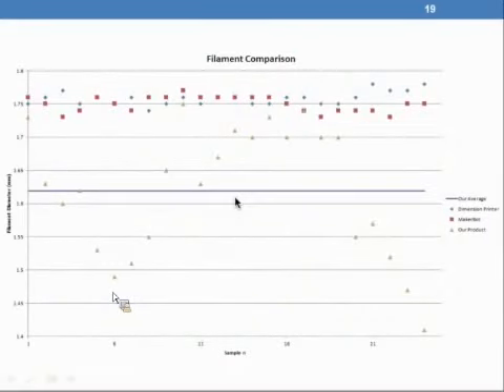Here's a slide that shows our filament quality compared to the purchasable commercial filament. Up at the top in the blue and red dots are the MakerBot and Dimension filament. They have a very tight tolerance control around their target diameter of 1.75 millimeters. On the other hand, our product doesn't nail our target diameter exactly, as far as we've gotten with our project, and we have a lot more variation in our product. Although it's hard to tell with the naked eye that our product isn't perfect, we do have a lot of variation. This data was collected by taking one data point per inch of 24 inches of filament, and those samples that are being passed around now are the samples that were used to collect this data.